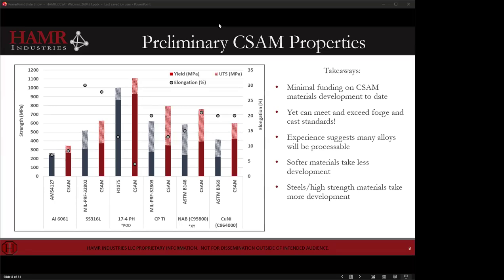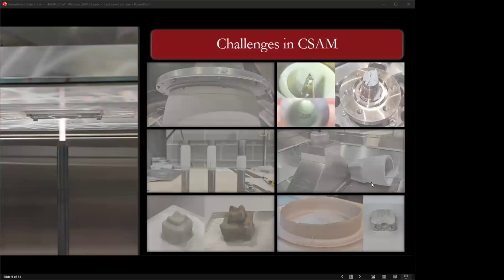17-4, a really high strength material that Pod's been able to make, and then CP titanium also looks pretty good. So there are some caveats. Harder materials, tougher materials are more challenging. That's definitely not the strength of cold spray. So if you want a really high strength steel, cold spray may not be your best bet, or at least look at it for a more traditional approach. But properties, we can make them.